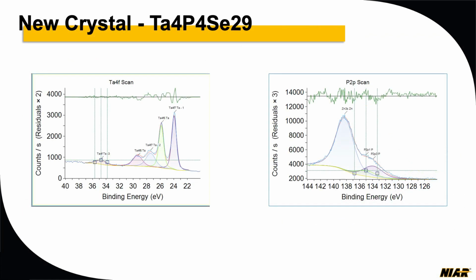Okay, so one of the other professors has created a different type of crystal. It's tantalum based. We have identified the tantalum, and we definitely need further analysis because it's not the standard tantalum 5 that we normally see. It's a lower oxidative state. So the professors are going to provide other samples for us to analyze. We also found that we have phosphorus as well. We have selenium data.